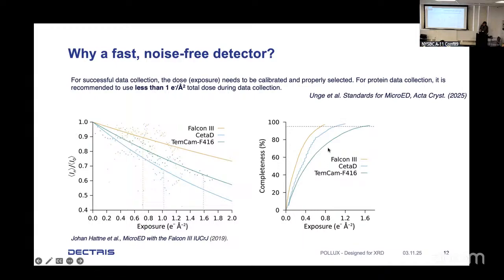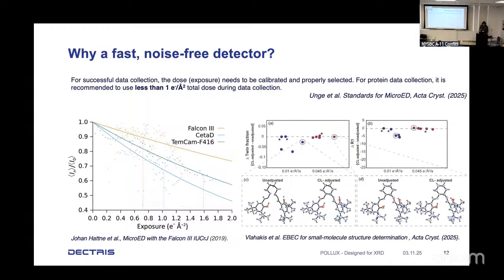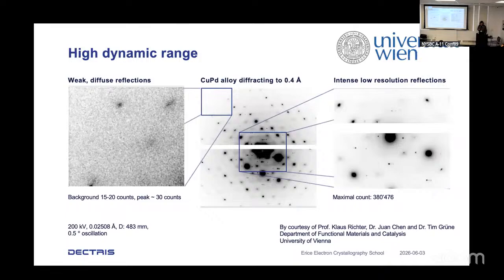And same for the completeness, the lowest noise contribution of the detector will give you the highest completeness at lowest possible dose. The other point is the coincidence loss because of the high count rate capability. This is a paper on data collection with the Apollo, and they argue a lot back and forth about how to deal with coincidences, and all these things are gone. I mean, you can count up to 10 to the 7 electrons per pixel and second. So you don't have to bother about coincidence loss. What you can bother about is your science and what you want to achieve. And so that really makes life much easier.